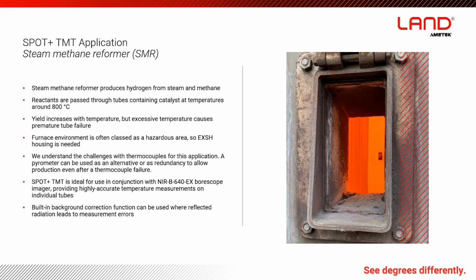So I probably don't need to go into the very basics, but steam methane reformers produce hydrogen from a steam and methane mixture, where you're passing that gas over catalyst at temperatures of 800 C. And that's what we're targeting. We're targeting those outer tube surfaces. The temperature of that surface is critical, and the window that we remain in is critical. If we're over that window, your tubes are not going to last very long. If you're under that window, you'll have a higher level of methane slip, which is indicative of low efficiency. And so accuracy with these pyrometers is really critical.